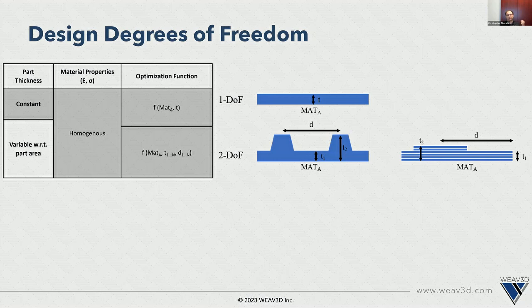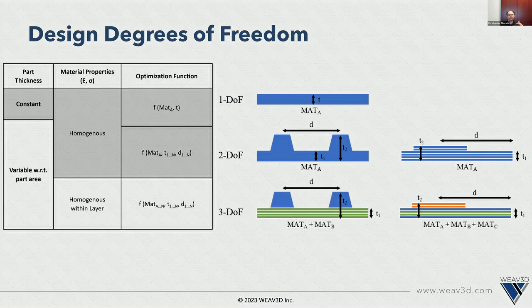So this is oftentimes things like injection molded plastics, where you have ribbing, or even laminate type composite structures where you can change the amount of plies in different areas of the part. Again, we're saying 2 degrees of freedom is a homogeneous material, so one material over the entire part, but we're changing thickness in different areas, and we're changing the distance between those thicker regions. So now we have some extra variables that we can play with. Now, 3 degrees of freedom is traditionally the limit for most composite designs.